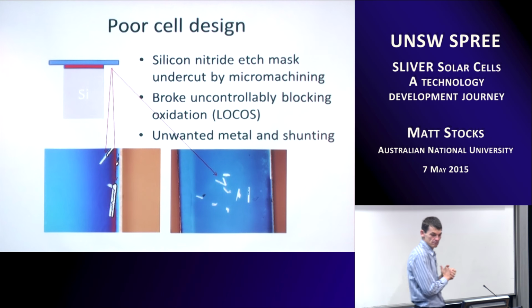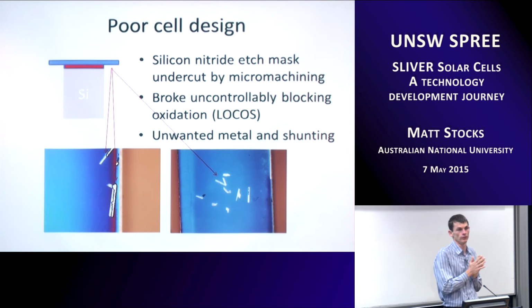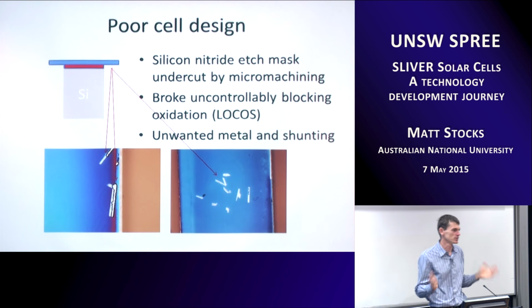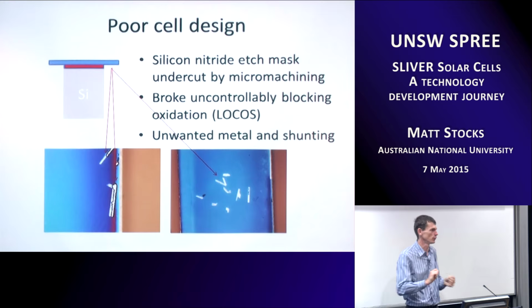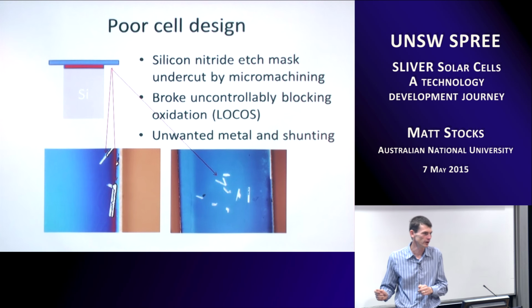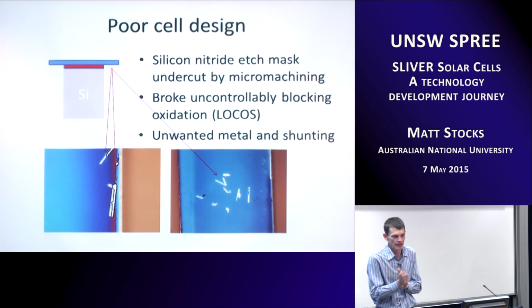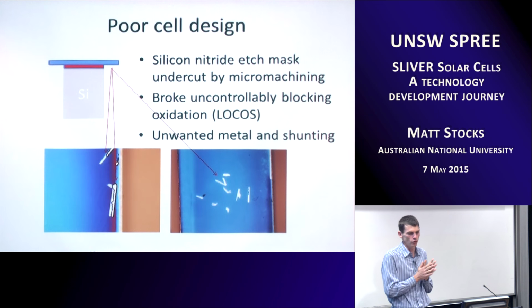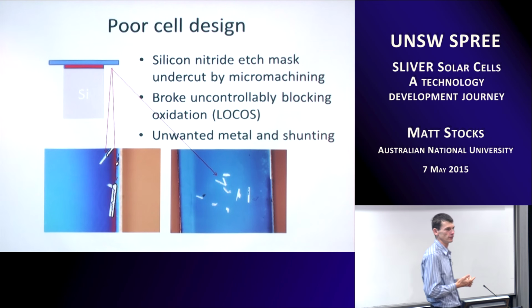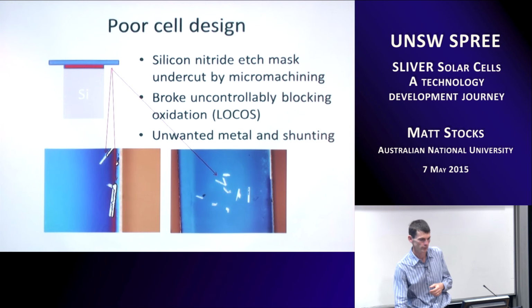We had a pretty poor cell design. We hadn't really thought through the issues. When we're building things in the lab, as long as some of them work, it's great, and we can sort through them and go, yep, enough of them work. Sometimes it does, sometimes it doesn't. And the biggest one that we got caught on was we were trying to use one of our masking layers for multiple purposes. We would keep using it for our etching process, and then we were trying to retain it later on to define where our contacts were going to go.